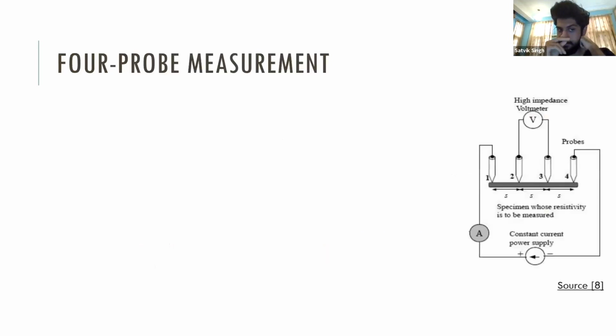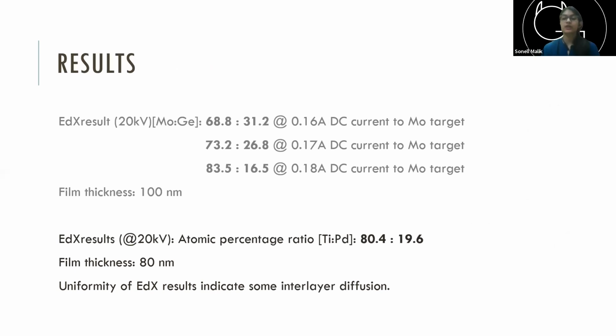Sonell, how is the thickness of the film measured? Oh, the thickness measuring of the film. There are 2 ways of doing that. The more efficient way is to use a quartz crystal microbalance. I have not mentioned it here, but what it essentially does is, a quartz crystal has a particular frequency of vibration, around 13.3 or 4 megahertz. You keep the quartz crystal in the same chamber as your substrate. When there is deposition on the substrate, there is also deposition on the quartz microbalance. As material keeps depositing on it, its weight keeps changing, which means the resonant frequency of vibration of your crystal also keeps changing. And there is a very efficient code to figure out exactly how much thickness has been deposited.